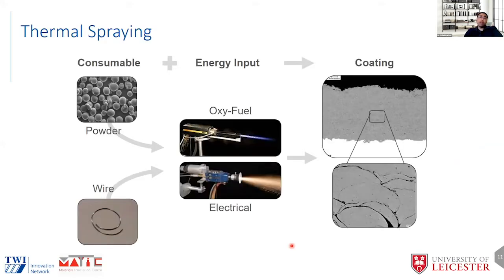So in thermal spray, the material that you're going to coat is in the form of a consumable. It could be powder or wire. You need an energy source, so could be a combustion source or could be an electrical arc. Oxy-fuel or fuel, or electrical energy, which provides the energy for melting or semi-melting of the particles, powder or wire. And these molten or semi-molten particles are propelled towards the substrate. They hit the substrate, impinge, expand, and they form pancake-shaped splats, and you build up a coating as you spray